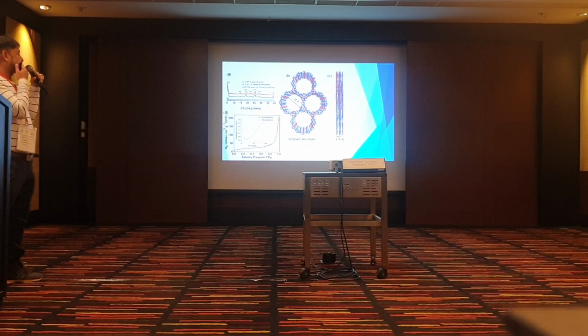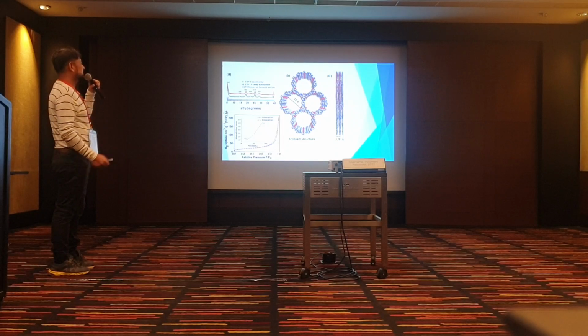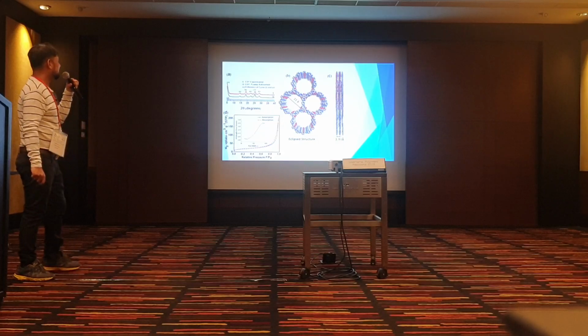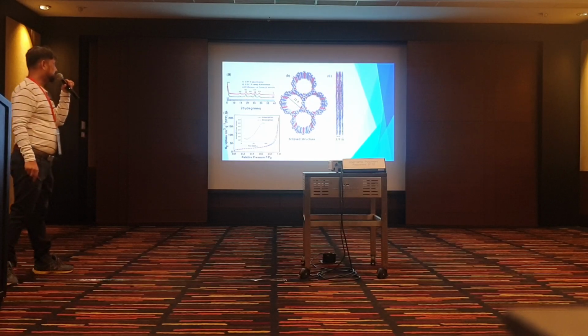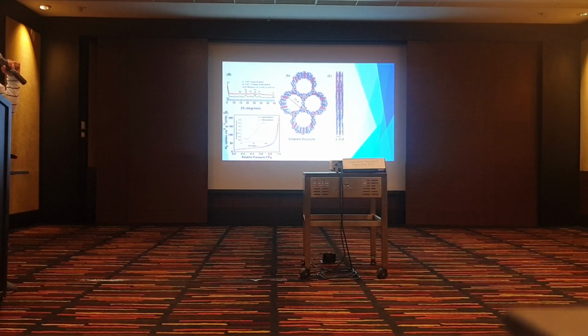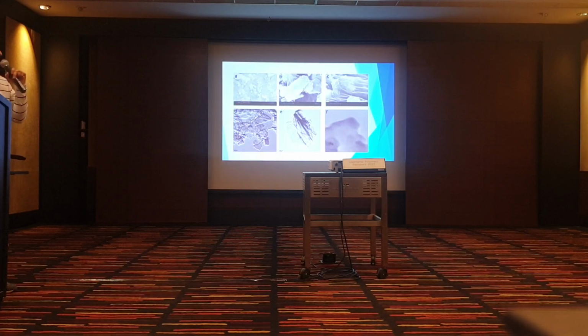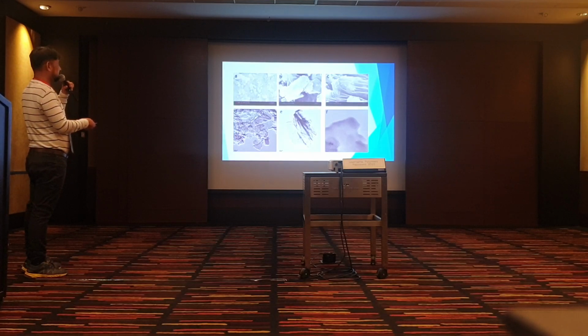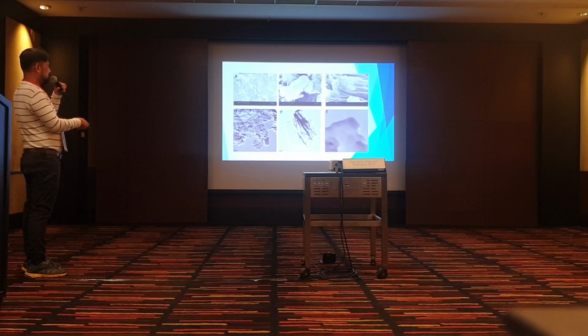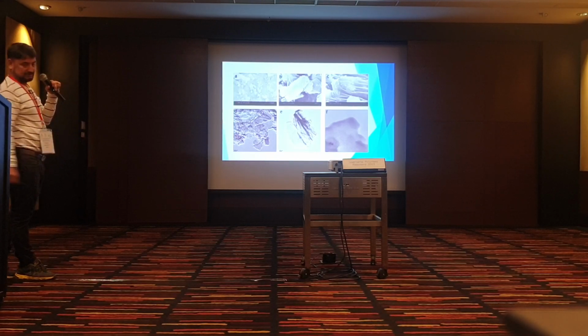So this is the characterization of this structure. Is this really a covalent organic framework or not? There are many characterizations we are doing here, and you can see here the porosity. It is a highly porous material. We give here the BET measurement, and the pore size is 22 Angstrom. Under AFM and TEM, it looks like a sheet. You can see this is the AFM image, a sheet-like structure, and here in the lower part is the TEM structure.